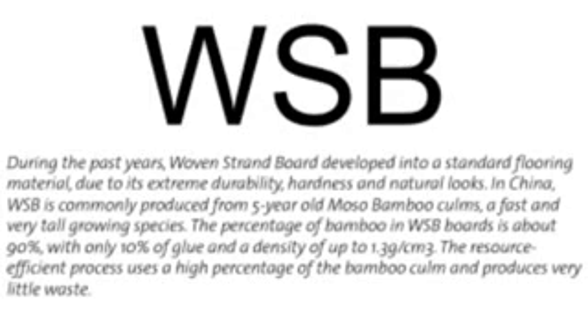But approximately 10 to 12 years ago, a new technology developed in China. And that technology is called the woven strand bamboo or woven strand board. To make a long story short, the Chinese found out that when you make very, very thin fibers out of the bamboo, so not using the bamboo as a stem as we know it, as a ready-made piece coming directly out of the forest, that these bamboo culms are split into small little bundles of fibers, then mixed with a resin or, let's say, a glue, and then pressed together as a composite material consisting of the bamboo fiber and an adhesive agent.